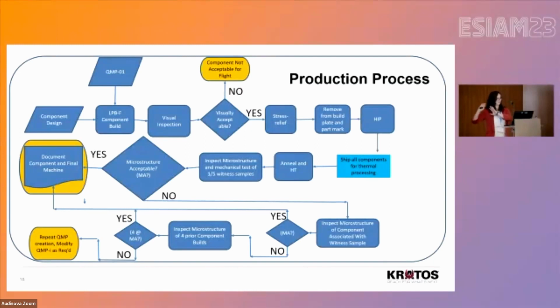If you find deficiencies in that 5th print, you go back and you look at your past 4 prints. If you determine that your past 4 were fine and your 5th one just happened to be an outlier, great, your process worked. But if you find deficiencies within your past 4, you need to stop and you go back and repeat the QMP process completely. So you define a new qualified metallurgical process, and those parameters get changed, and you now have a QMP-2, and then you can move forward.